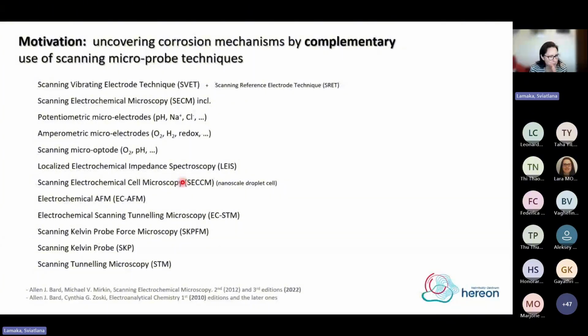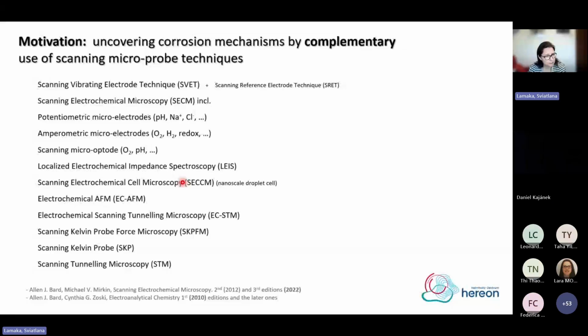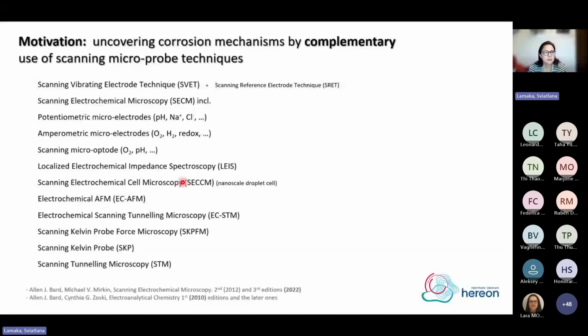And anodic oxidation also leads to pH change, apart from strong ionic fluxes. In this case, this is local acidification due to hydrolysis of ions that are formed as a consequence of anodic oxidation. This hydrolysis might lead to rather significant acidification, depending on the hydrolysis constant, which is related to the stability constant of the hydroxide. This acidification is especially pronounced for aluminum-based and iron-based alloys, and it is basically what drives pitting corrosion for these metals. So these are the changes that we will try to catch with the techniques that I present: local pH changes, ionic fluxes, and evolution of hydrogen and consumption of oxygen.